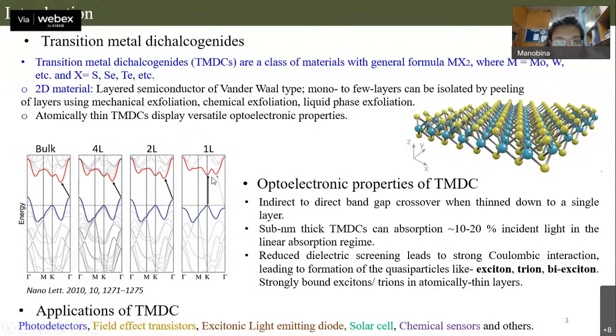So due to change of thickness, the relative energetic position of these valleys changes. Why? So it is due to the interlayer coupling. So when there are two layers, the interaction is different. Like this conduction band is made of px plus i py. Like you already mentioned, this can be easily peeled off layer by layer, right? The interaction is relatively much lesser. But due to this change in number of layers, there will be change in energy positions in the conduction band due to some interlayer coupling.